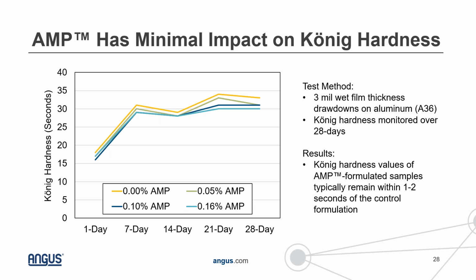We also looked at a couple other properties. Coating hardness is something that we monitored over time, after 1 day of drying and then up to 28 days of drying. So you can see the hardness development in this formulation.